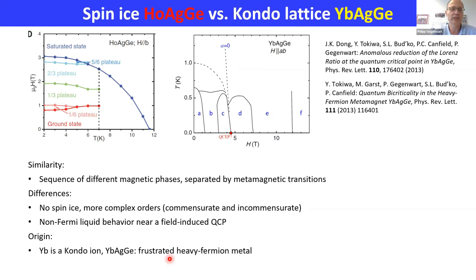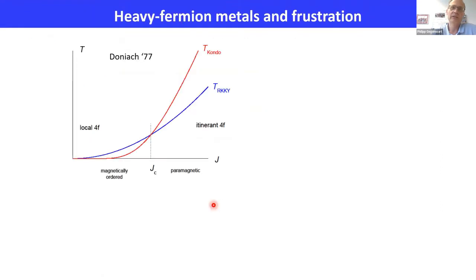And more importantly, there is non-Fermi liquid behavior and field-induced quantum criticality at the edge between two such phases. So that's an example now for such a Kagome magnet where the magnetic moments are Kondo ions. And for Kondo materials, of course, we know that there is a competition between the long-range magnetic exchange interaction and the on-site Kondo effect. And this competition leads to interesting behavior and, for instance, quantum criticality.